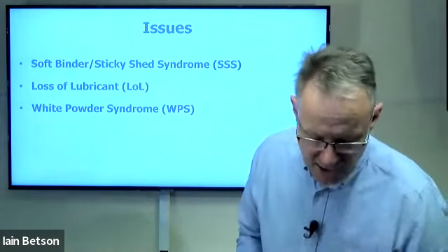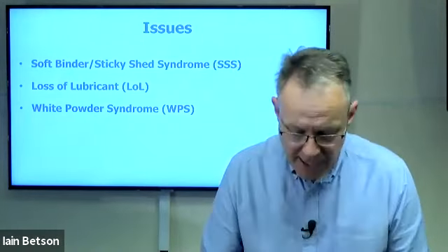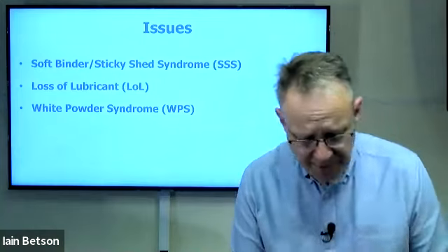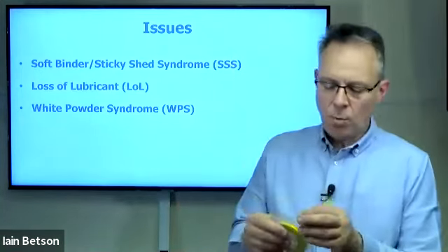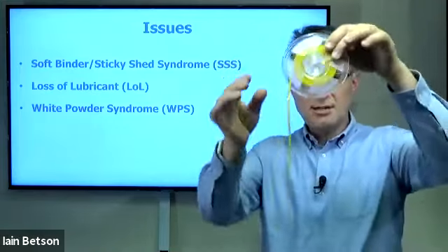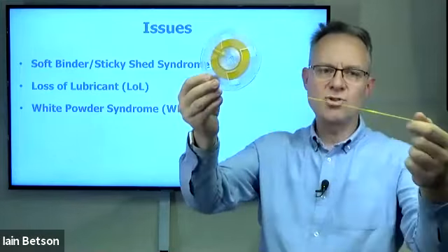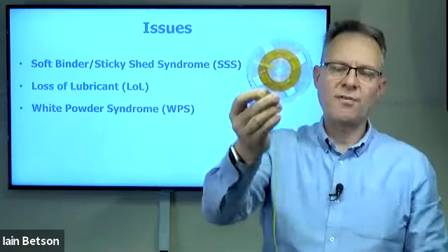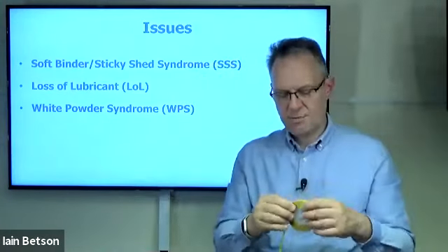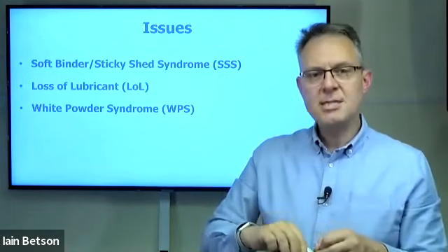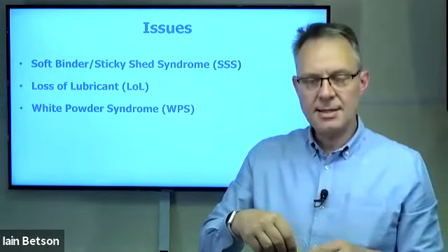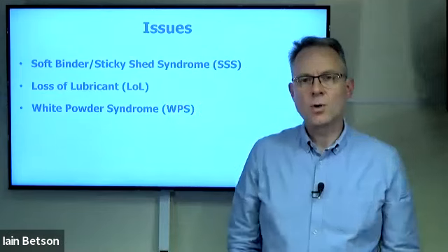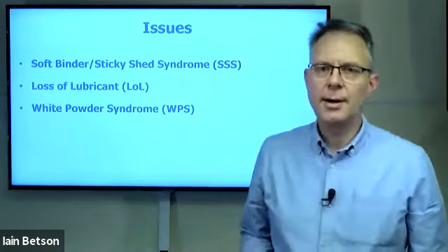A good test to see if a tape survives sticky shed syndrome is to see if it drops off the reel okay. I've got a reel of tape here. Actually, I'll try it with his leader tape just to demonstrate what I mean. This leader tape obviously has no oxide and no binder on it and will just drop off. If your normal recording tape does that and falls off, that's a good indication that it's not suffering from sticky shed. However, it's always best to be safe, to check it fully, physically examine it, and you might need to subject it to what we call baking, and I'll come on to that, in order to preserve it.